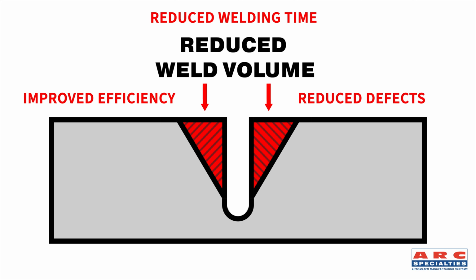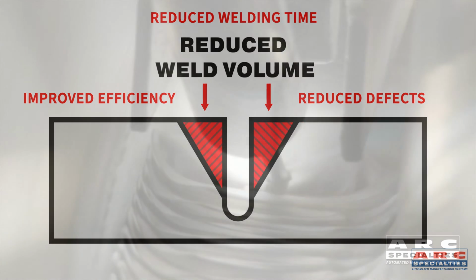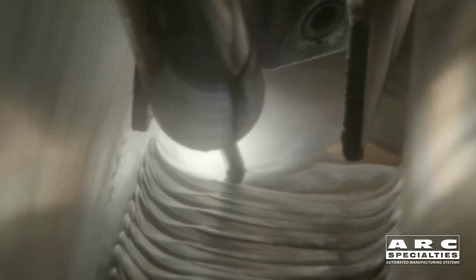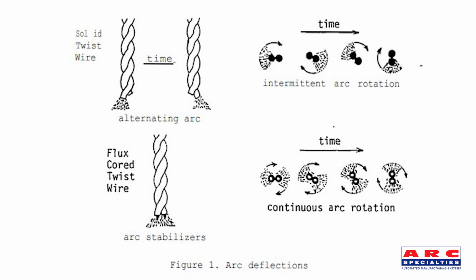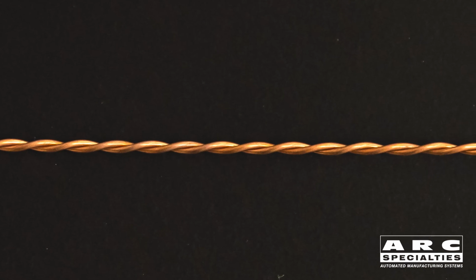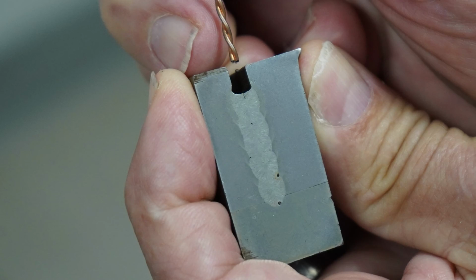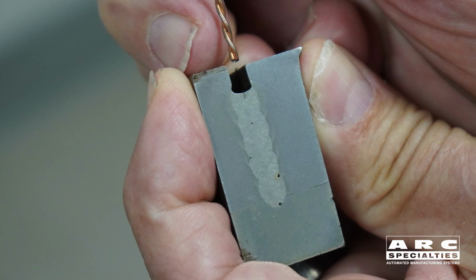This is something I've been working on literally for decades. My first experience with narrow gap welding occurred back in the early 80s when I was working in a welding research laboratory and we were trying to reduce the weld volume of a weld groove on a rock bit. Kobe had just patented a clever system using twist wire. They used two .093 diameter wires twisted together. By feeding this .093 twist wire into the groove, in effect, rotated the arc and wetted the walls.